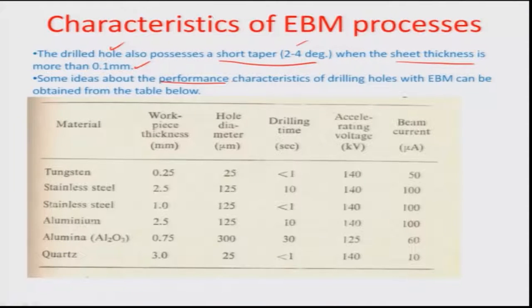So these are some performance parameters about the drilling of holes with different work pieces. For example, if you are drilling in tungsten, stainless steels, aluminum, alumina, quartz, you have different work piece thicknesses, hole diameters, drilling times, accelerating voltages and beam currents which are given in this particular table. So you can see the very, very high accelerating voltages which have to be hit upon for drilling. Not very high thicknesses, in the range of 2.5 mm to 1 mm, and you have excessively high drilling time, particularly in stainless steel, about 10 seconds for drilling about 2.5 mm workpiece thickness. So if you compare it with conventional drilling, you can find out how much more energy will be consumed in drilling this. But obviously, because such processes are meant for extremely complex contours or shapes, or even to some extent alloys which are otherwise hard to machine, you can still consider the EBM process, although it's energy expensive in comparison to conventional processes.